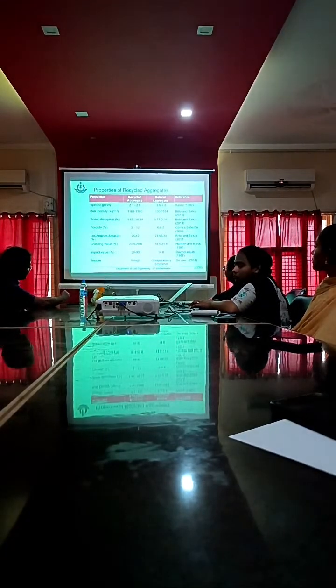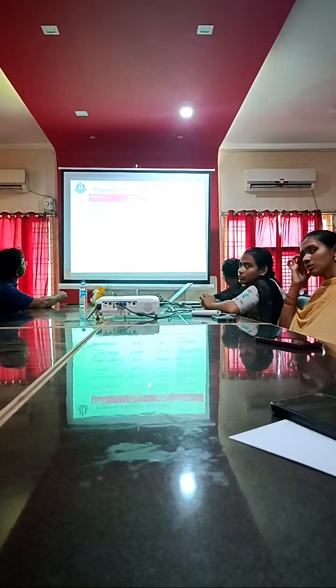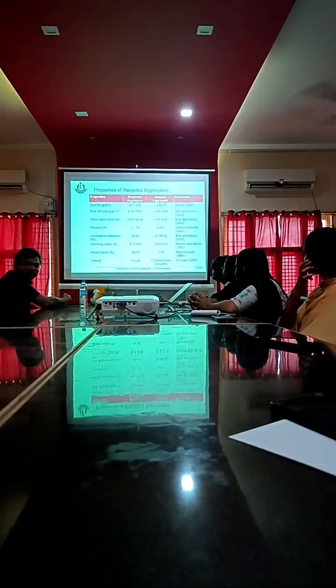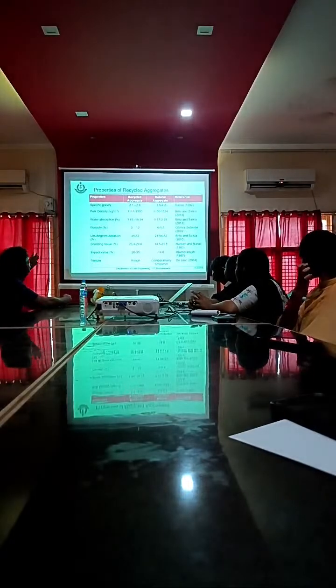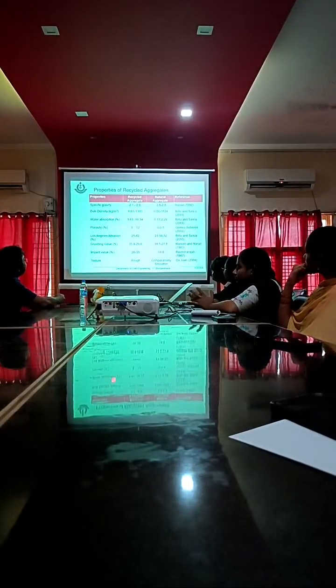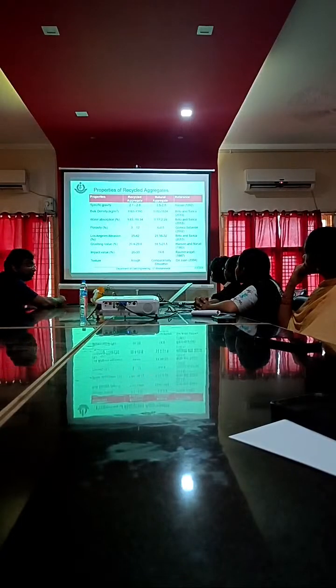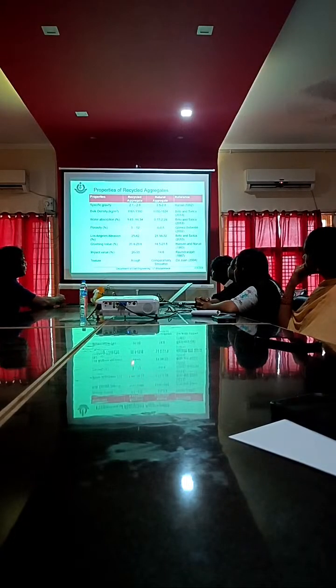So whenever you use the aggregate, thoroughly determine all the properties of this aggregate. The specific gravity you see is somewhere around 2.6, and the natural aggregate is somewhere around 2.8. It has already undergone some life, 20 years, 25 years. Because of the mechanical grinding also, the aggregate might be slightly weak. Bulk density is almost nearly the same. Water absorption is more. Why? Because of the attached water, the water absorption is more, the same as in the case of fly ash aggregates, where water absorption is also recorded as more. The porosity is also slightly more compared to regular natural aggregates.